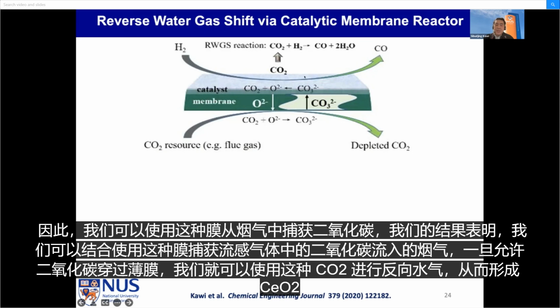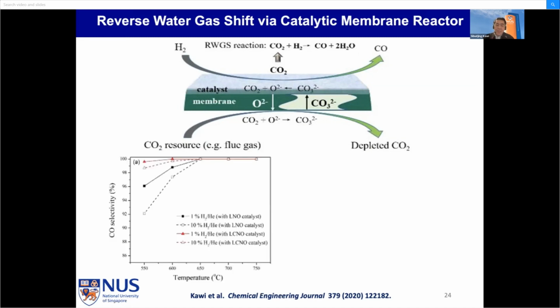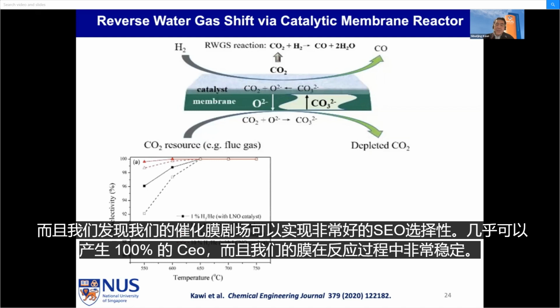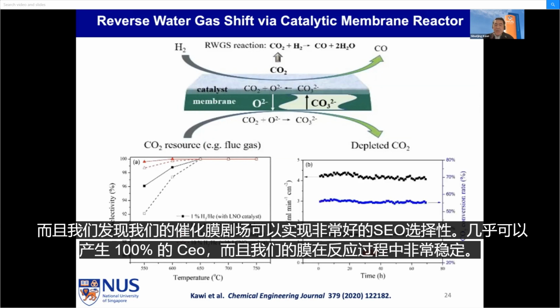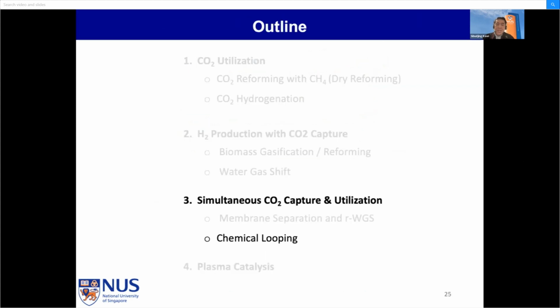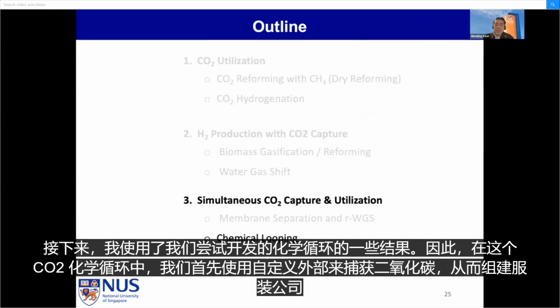And once the CO2 is permeated across the membrane, we can use this CO2 for the reverse water gas reaction to form CO. And we have found that our catalytic membrane reactor can achieve very good CO selectivity, almost 100% CO can be produced, and our membrane is very stable during the reactions. Next, I will show you some results on the chemical looping that we have tried to develop.